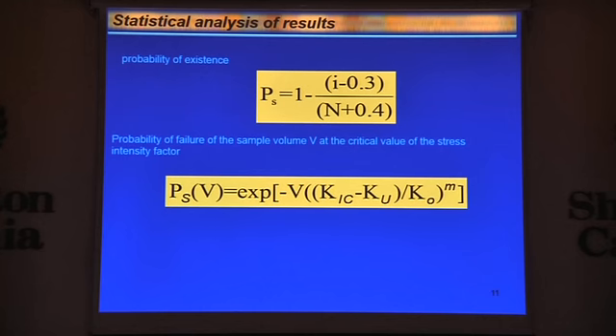And as you know, very powerful is the Weibull distribution, especially when you have only a few specimens. At least you should have 3. Here we use this Weibull distribution, where i is the current specimen number and N is the total number of specimens. We use the current value measured by the fracture toughness test. This is the value of fracture toughness